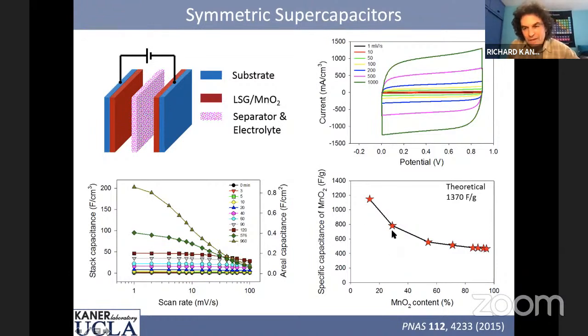And when we look at this, the theoretical capacitance of manganese dioxide is 1,370 farads per gram. And so if we use a lot of graphene, on the order of 90%, and around 10% manganese dioxide, you can see we can get out about 1,200 farads per gram. So we start approaching this theoretical limit. Now, keep in mind that manganese dioxide is an insulator. So by itself, you couldn't get anything out of this. And so we're using graphene as a scaffold to extract all the energy out of manganese dioxide. So that's quite good from a theoretical level.